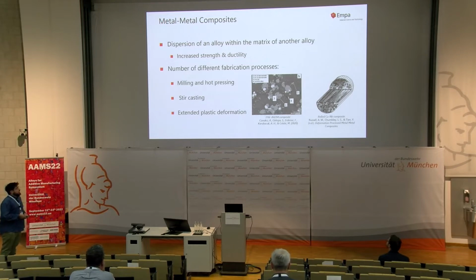Until now, I have seen in the literature multiple different fabrication processes used for the production of these composites. In many of them, at least one processing step includes the use of powder metallurgy. So it is quite common to pre-mix the different powders and then form the structure with a process like milling or hot pressing, where based on the composition that we have, we know there is an expectation for a specific volume fraction of the dispersion phase.